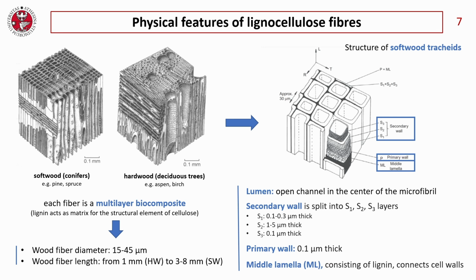But going more into detail, you can see that we have a fiber in which we have the middle lamella consisting of lignin that connects the cell walls of this fiber. The fiber is formed by a primary wall outside, and inside we have the secondary wall that is split into 3 layers. The secondary wall is responsible for the mechanical properties of this lignocellulosic fiber. In the central part we have the lumen, that is an open channel in the center of the fiber.